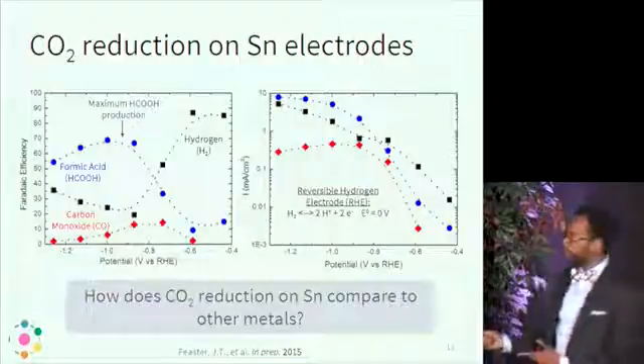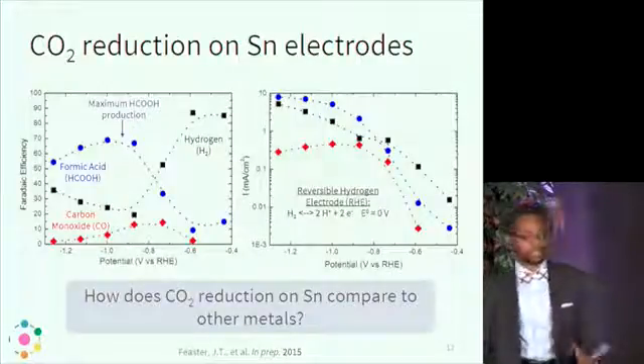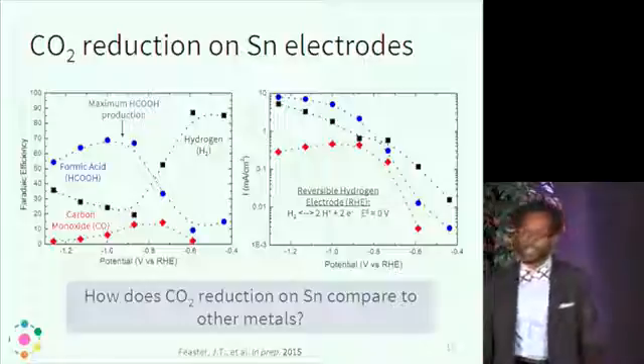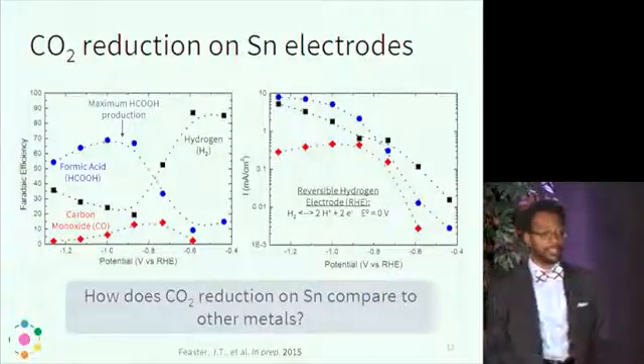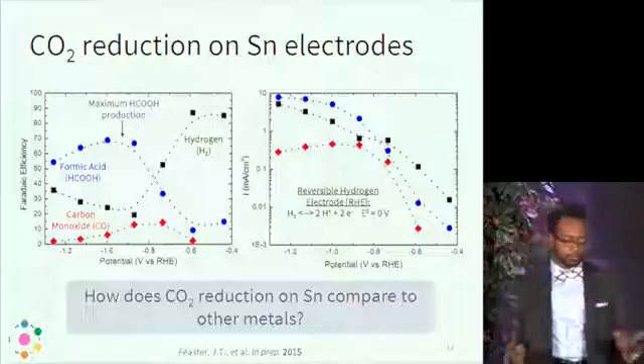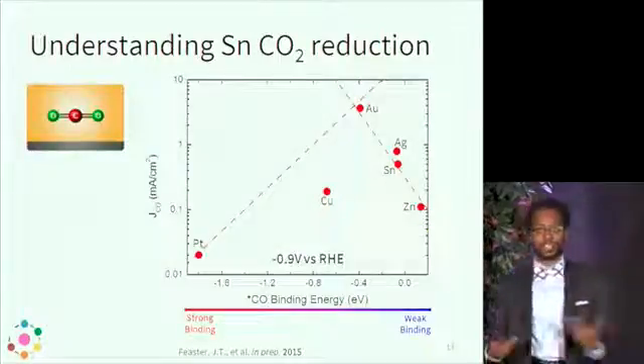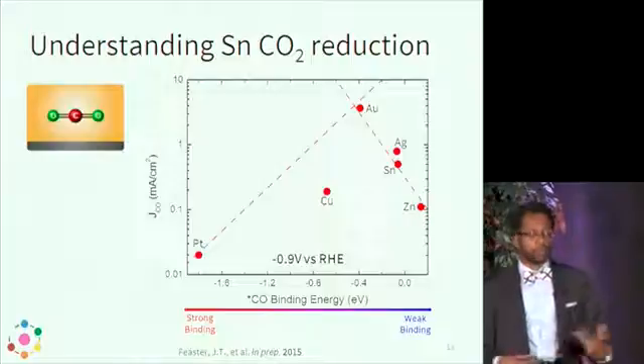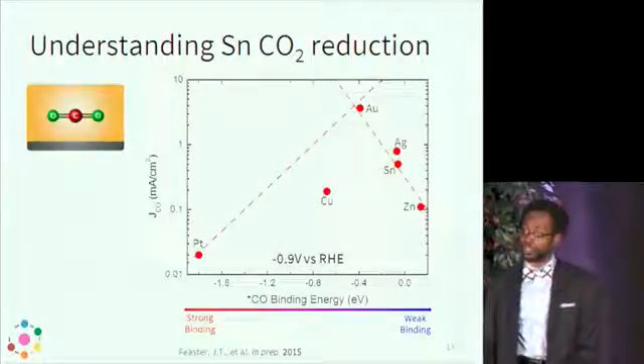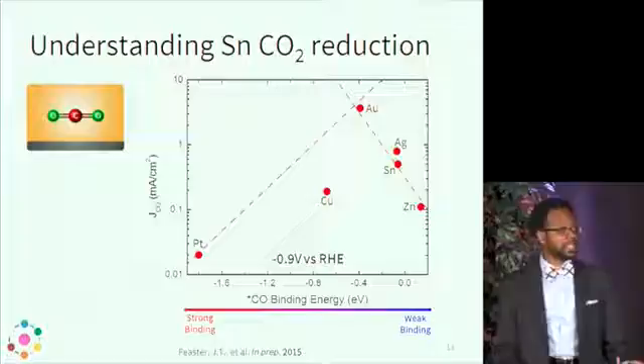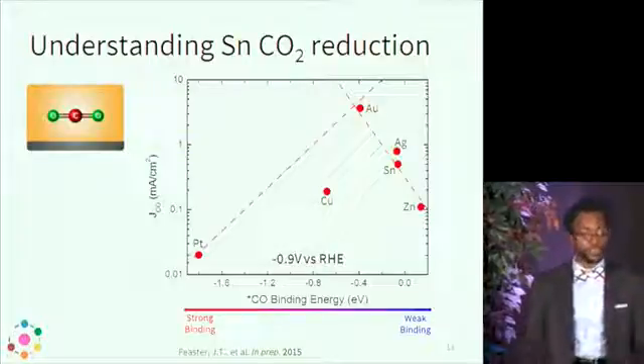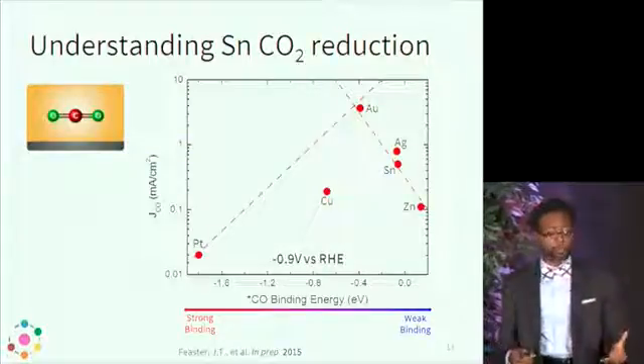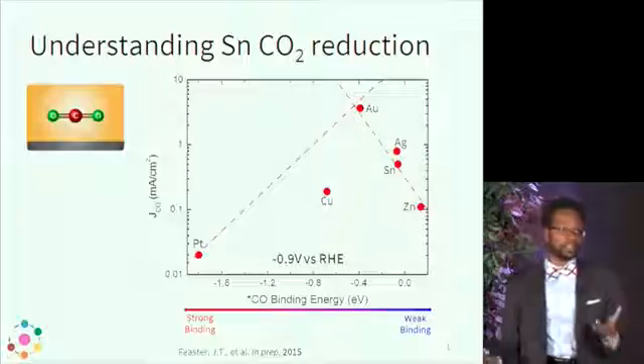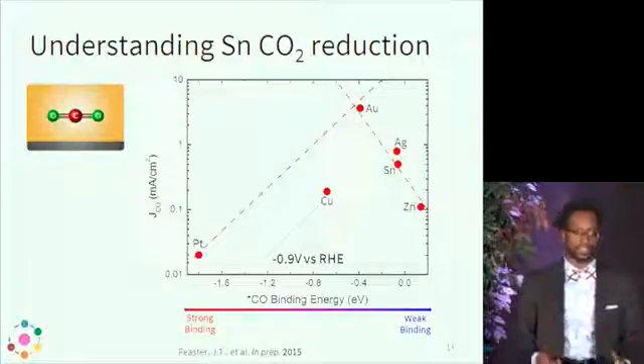But it still leaves out this major question of how does CO2 reduction on these tin electrodes compare to other metals in the exact same system, in the exact same setup, and can we learn anything from that analysis? And so what we did was we actually partnered with some collaborators in the Norskov group, which is another group in the chemical engineering department here, and we did density functional theory calculations, or DFT calculations, to be able to then compare experimental data along with theoretical data and calculations to see if we can gain any insight from this